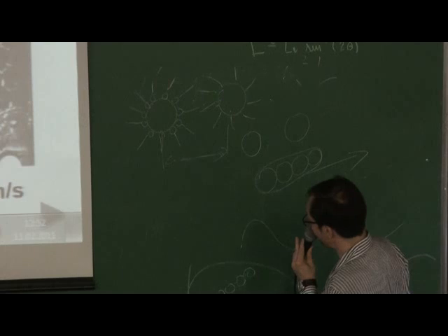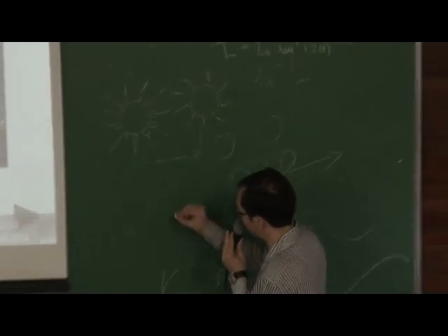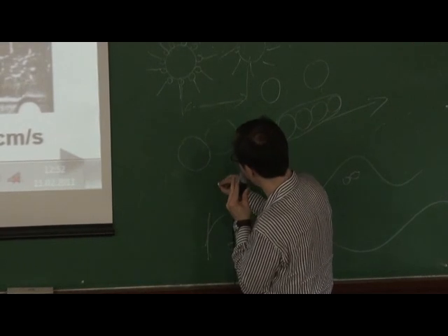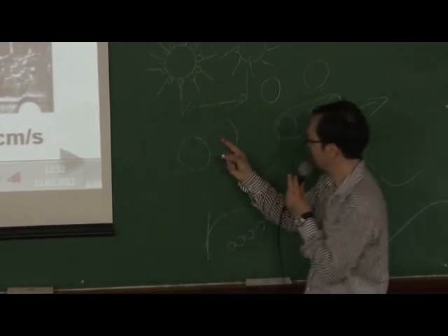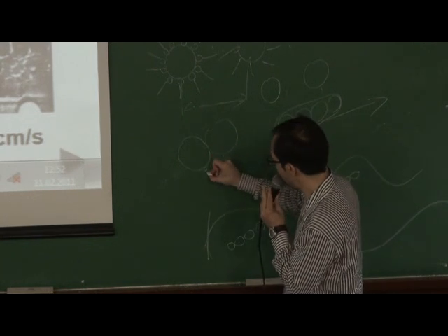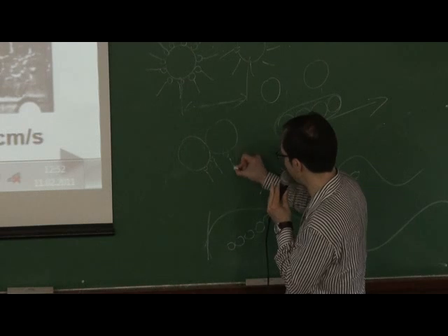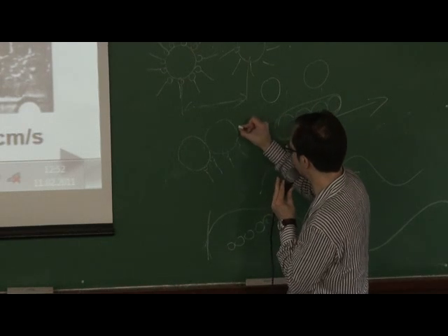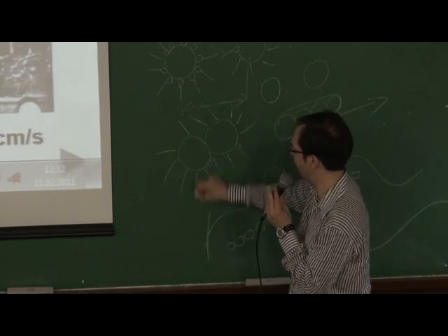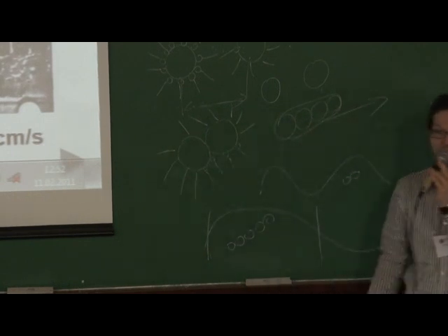But it happens that during the production process something is created which is called a primary agglomerate, which means that these particles are agglomerates and later covered by the tensides. These are these guys. And especially in water-based ferrofluids you're getting these guys.